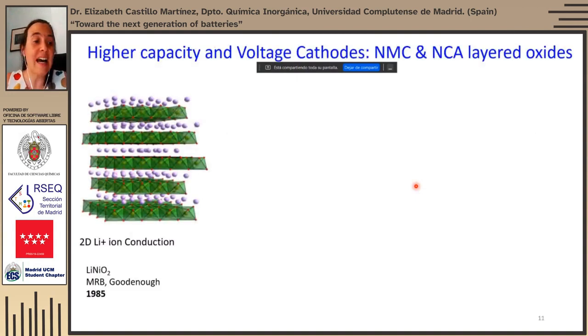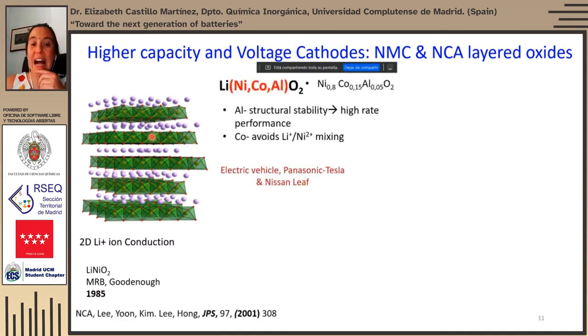Starting from the lithium cobalt oxide, replacing cobalt by nickel led to higher capacity, because in lithium cobalt oxide, only half of the lithium ions could be reversibly extracted. With nickel, you can achieve a larger amount of extraction. However, they have a high reactivity towards the electrolyte and also high thermal reactivity. So strategies involving doping, such as with cobalt, which avoids the lithium-nickel mixing that occurs in the pure composition, or doping with some electrochemically inactive elements such as aluminium 3+, allow materials with high rate. Actually, this composition is used in many commercial batteries, and you will hear of it as NCA.